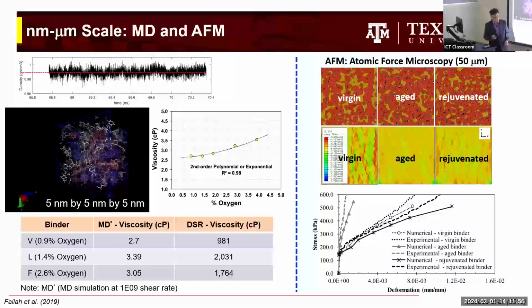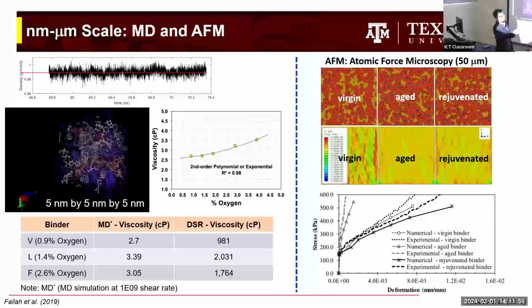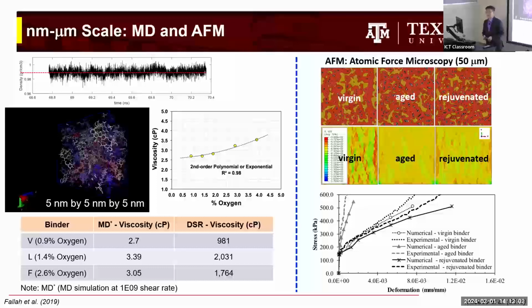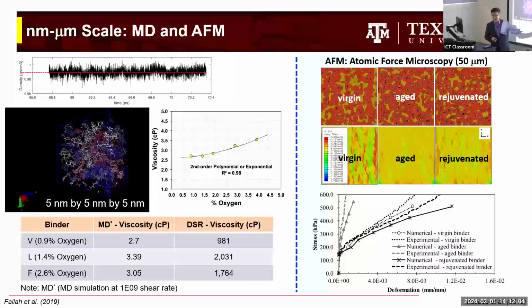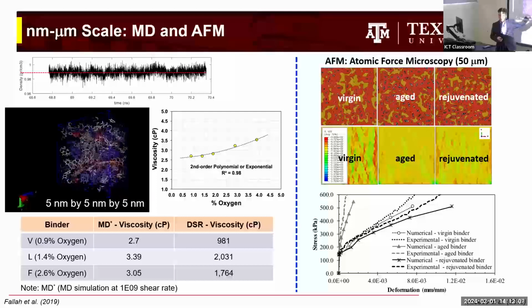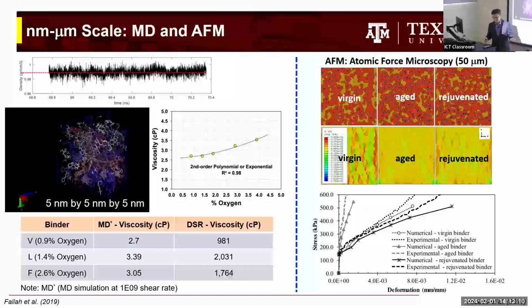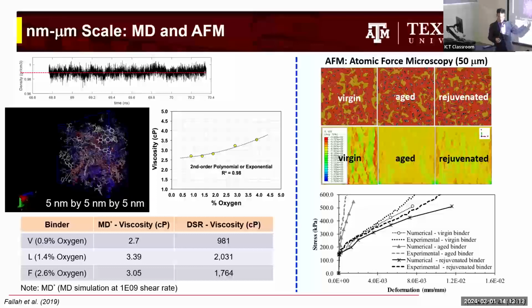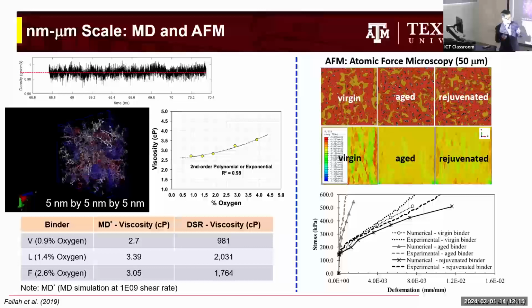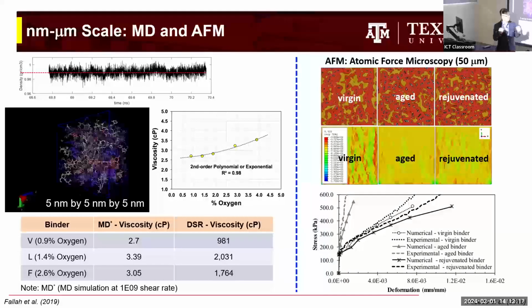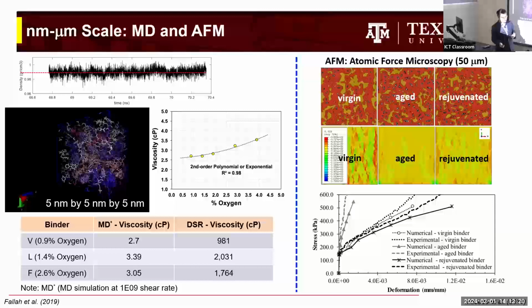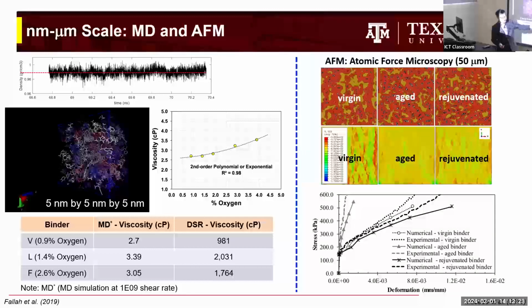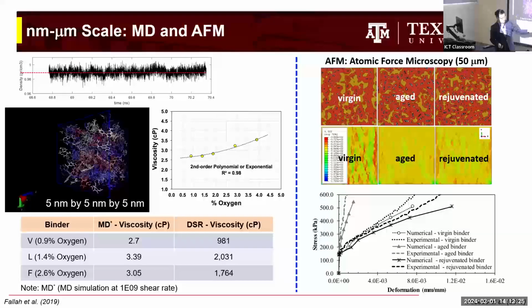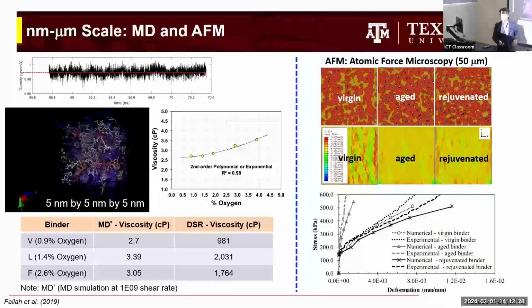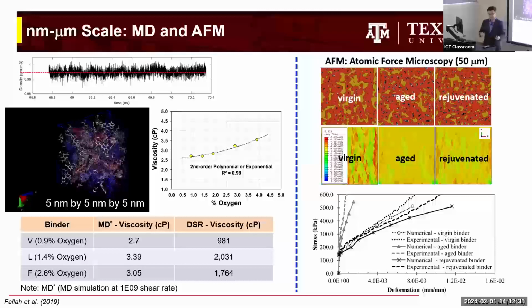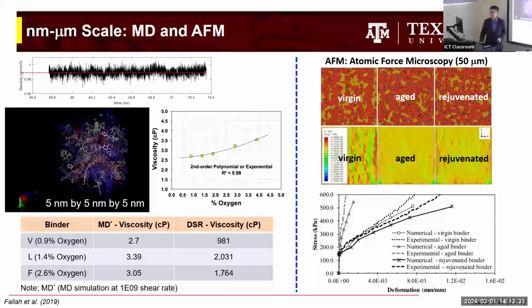And then the other way, we did atomic force microscopy, which is now more continuum level. At the continuum level, micromechanical modeling and prediction works very well compared to MD, which is not continuum level. So we could compare experimental and computational results, by finite element simulation, for three different binders: virgin, aged, and rejuvenated. And the micromechanical modeling works generally well at that scale.